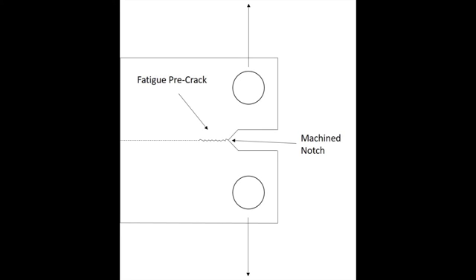And the last thing we'll look at here is what's called a compact tension specimen. And it's basically a square block, and it's a little bit longer on one end to have some pinholes, and then has a machine notch in it. And from that notch, we would normally cycle the part up and down and up and down, pulling on those pinholes, and create what's called a fatigue pre-crack. And this is really important for evaluating an engineering property called fracture toughness. And that's a material's resistance to crack propagation. But for the demonstration here, we're just using a machine notch without the fatigue pre-crack. But it still results in a pretty cool pattern.